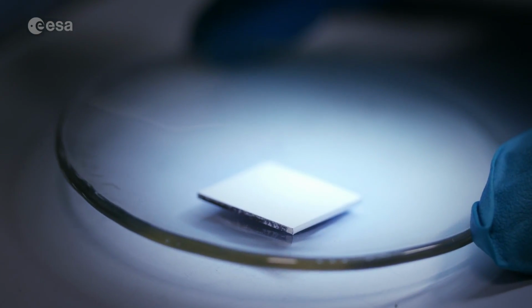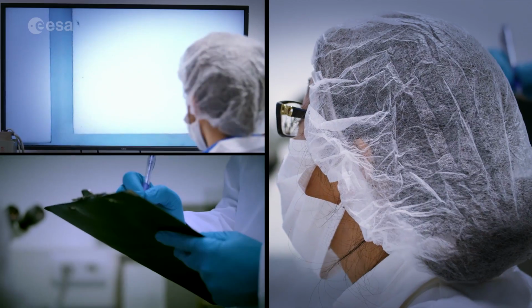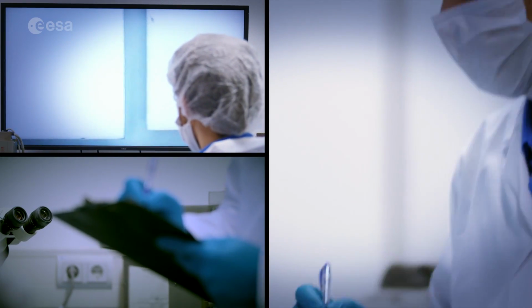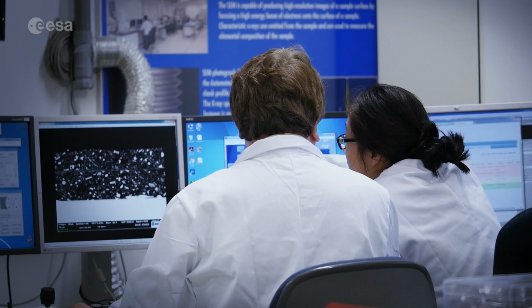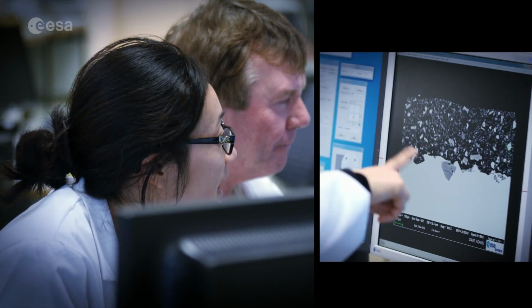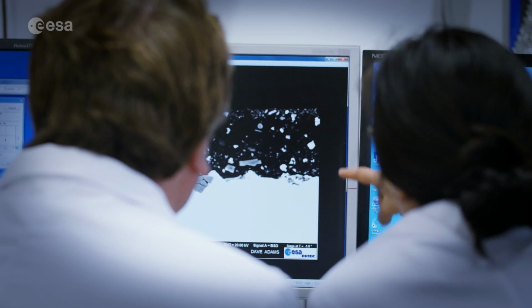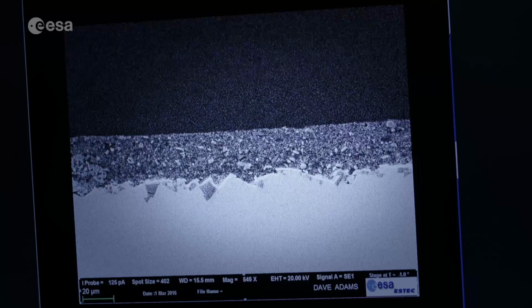After the initial test, we identified two prospective ceramic white coatings which showed quite good resistance to high temperatures and UV radiation. These coatings were later tuned with a specifically doped coating so we could reduce the radio interference. Of the two coatings, we used a range of methods to achieve samples with different thicknesses and different adhesion strengths. For us, the challenge was the risk of cracking of the coating, and for that we had to analyze the surface with a sophisticated electron microscope.